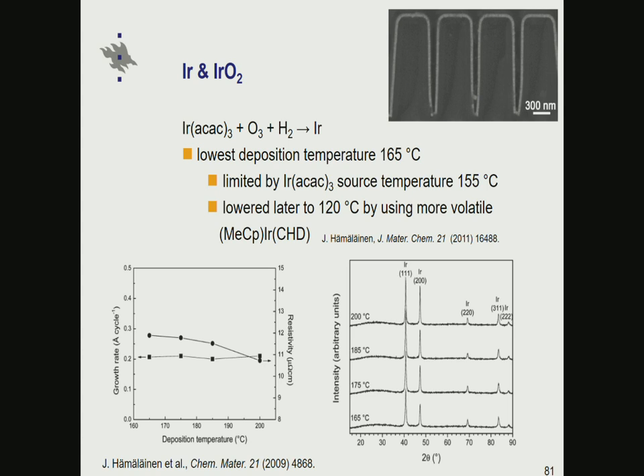But if we first have iridium acetylacetonate, then add ozone to make iridium oxide, and in the next step give a hydrogen pulse, we are reducing the iridium oxide. So we can lower the deposition temperature of metallic iridium to 165 centigrade. Otherwise it requires at least 200 centigrade. This 165 limitation was coming from the iridium acetylacetonate source temperature. But then we went further and developed a new iridium precursor, a heteroleptic compound that we could evaporate at lower temperatures, and then we could also lower the deposition temperature of metallic iridium down to 120 centigrade by using this new metal precursor, ozone and hydrogen.